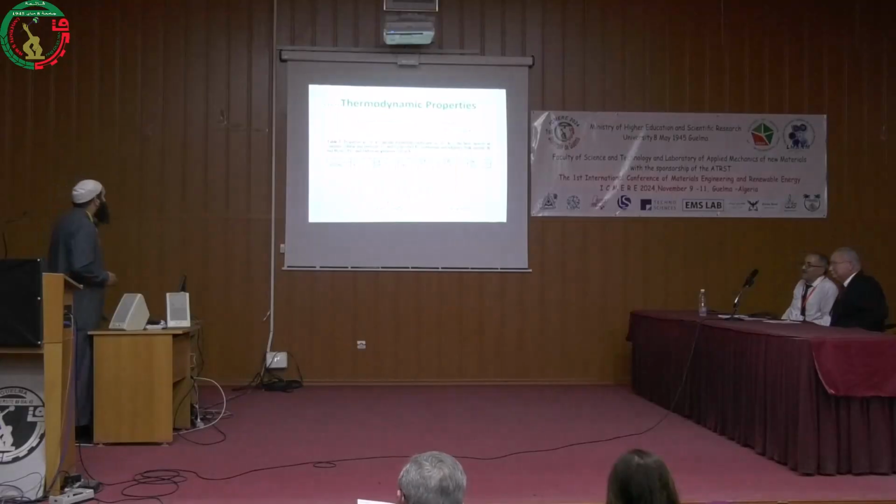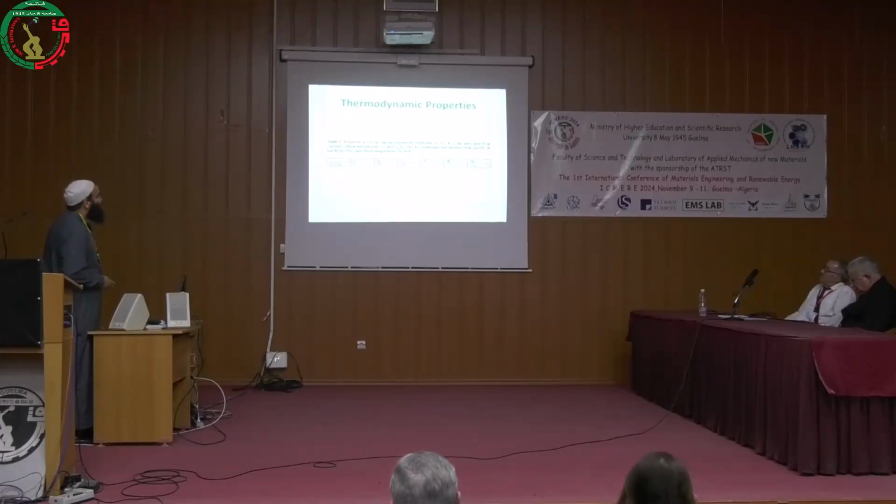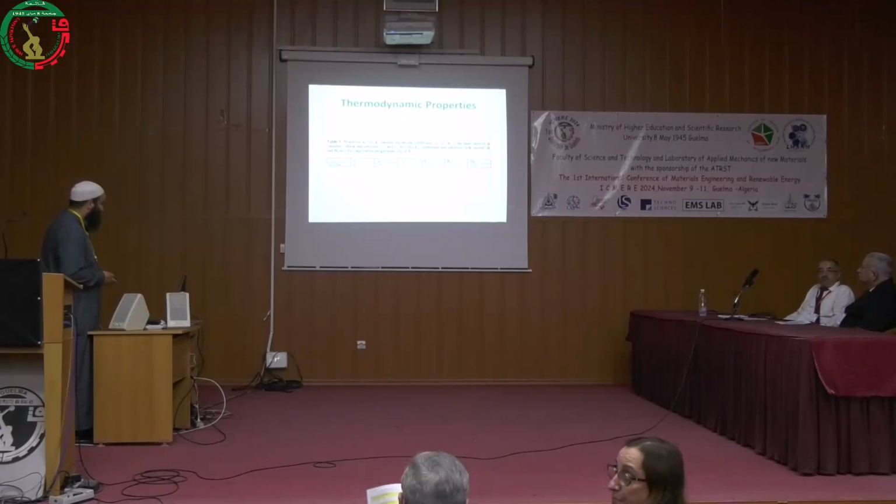So let's move to thermodynamic properties to have an idea about thermal conductivity. Here we evaluate heat capacities, they are close to each other. And here is the bulk modulus at 300 Kelvin. Again we have very small values, which means that we have a very soft material. And we do not have a very large value of Debye temperature, which means that we will have weak thermal conductivity, which will be very beneficial for thermoelectric performance.